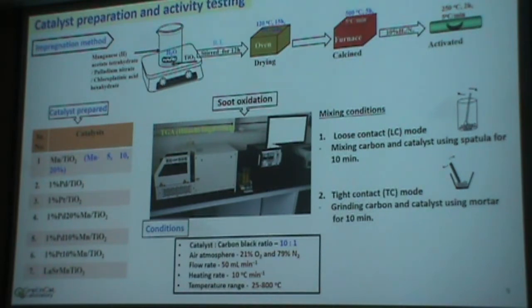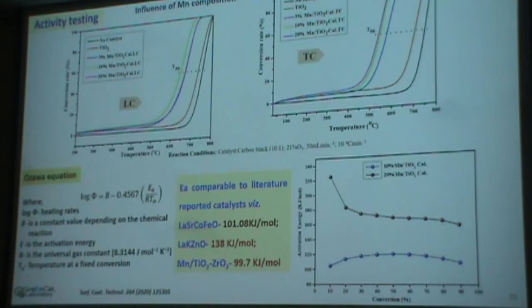Actually, we have prepared different types of catalysts in order to compare their activity with the Mn, and activity testing of these catalysts for soot oxidation was carried out by simple TGA-DTA analysis in both loose and tight contact mode. And these are the results. Initially, we checked the catalyst with bare TiO2 and then changed the Mn composition in both loose contact mode and tight contact mode. As you can observe, the Mn loading is increasing up to 20%: 5, 10 and 20, we changed the Mn concentration.